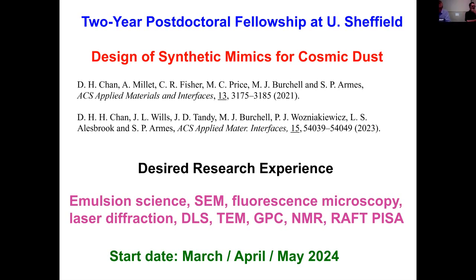We've done some work on designing particles for foam stabilization, but those are older studies. They don't involve PISA. The air-water interface is typically characterized as being anionic and hydrophobic, so what we've done in the past is design cationic particles which would stick to such surfaces. Cationic particles like that would be terrible emulsifiers for oil, but for nanobubbles, maybe. I guess, how would you generate them? By ultrasound?